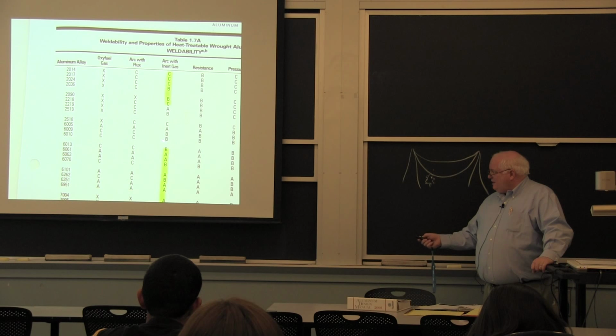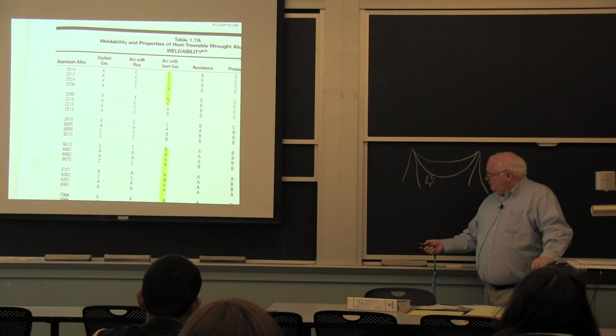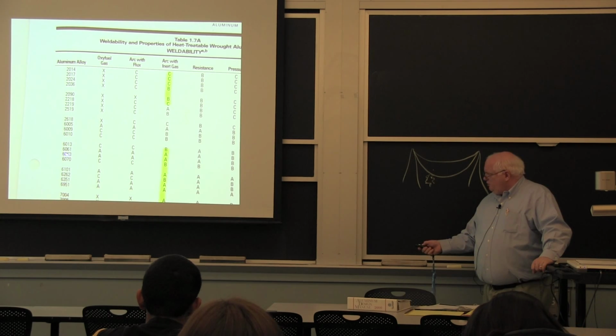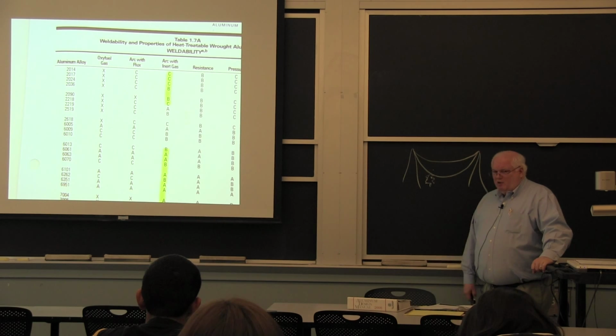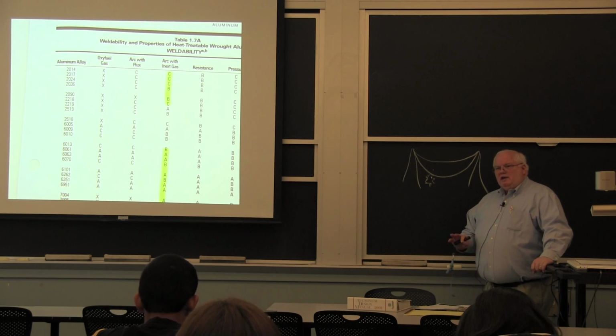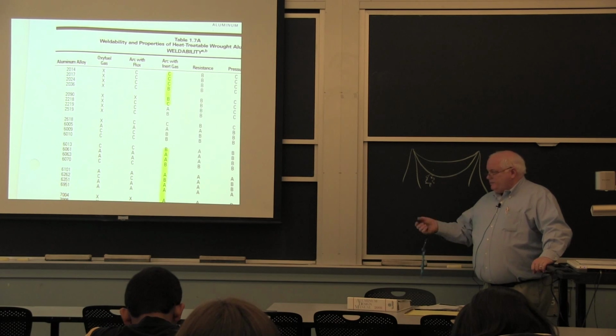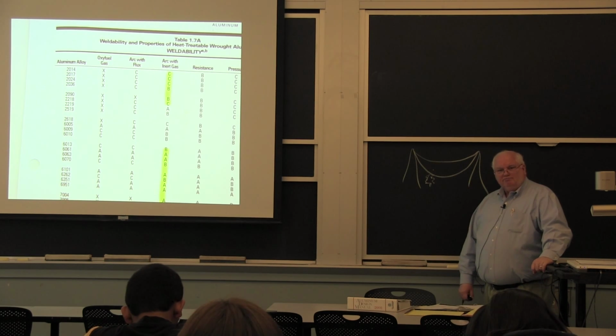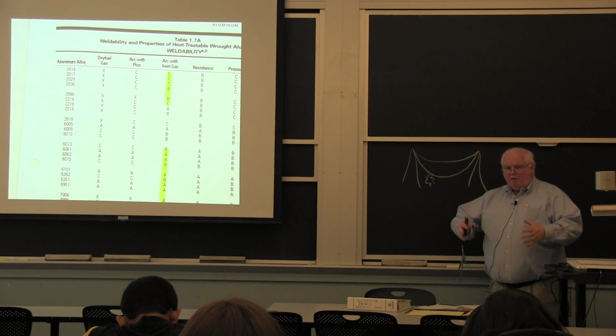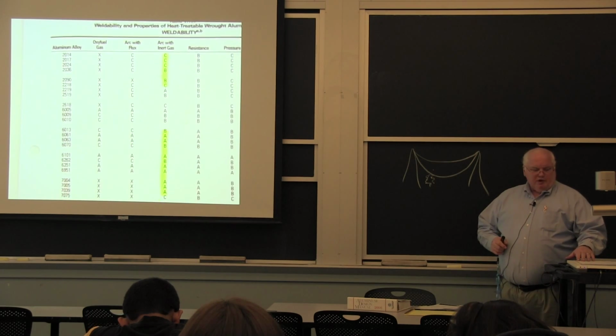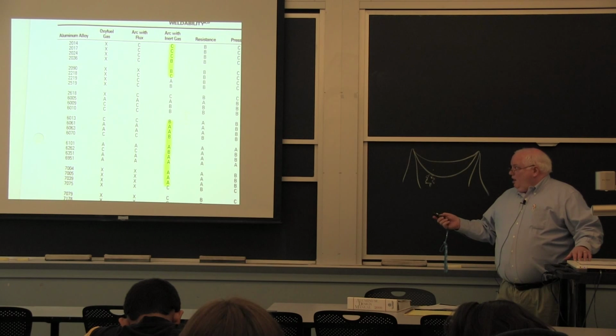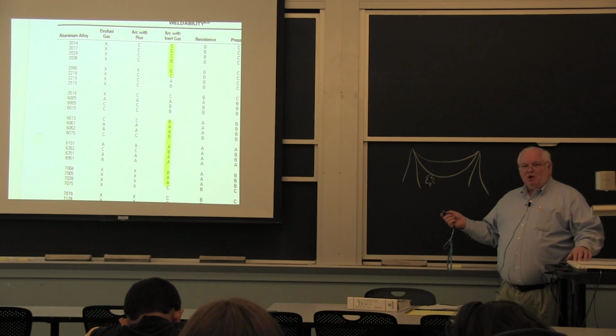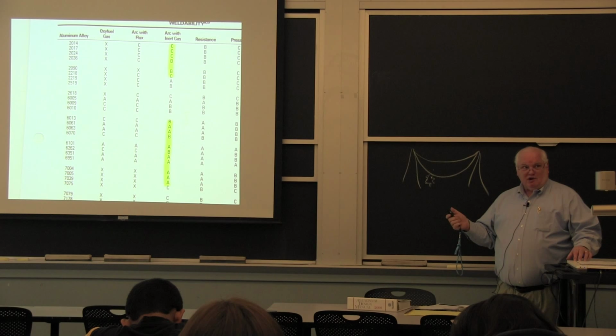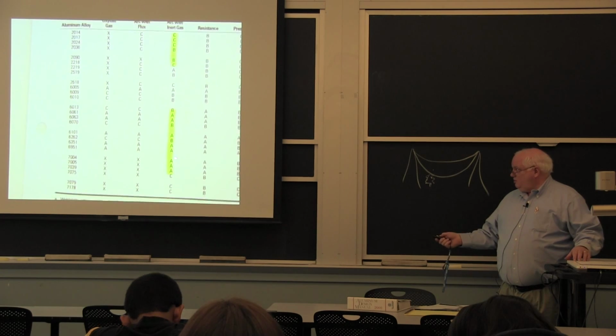Okay, if you get down to the 6000 series, you get a lot of A and B weldability. 6061 and 6063. The difference, this is typically plate or sheet, and this is typically extrusions. They have A grade weldability. The largest tonnage of aluminum alloys is 6061. Okay, architectural aluminum, door frames, window frames, you name it, you can get good strength in the base plate, but we're going to see you only get about half the strength in the weld because it's heat treated.